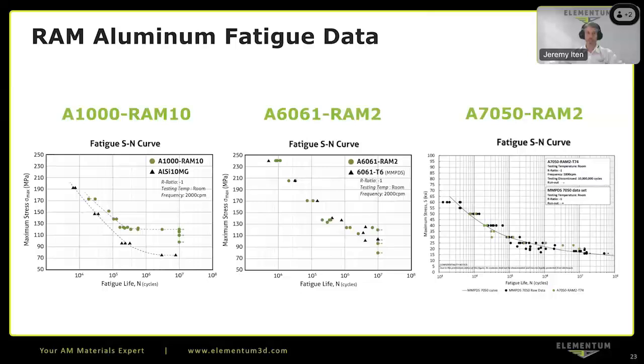Here's some other fatigue data for an A1000 RAM 10. It's compared against an AlSi10Mg printed material for comparison. And then a 6061 RAM 2, which is the material we've been talking a lot about with the ACO blown powder DED work. You can see that the green is the RAM 2, and it's being compared against the MMPDS aerospace data for the traditional wrought 6061 in the T6 heat treatment condition. And especially at the higher cycles, you can see that the RAM 2 material compares quite favorably.